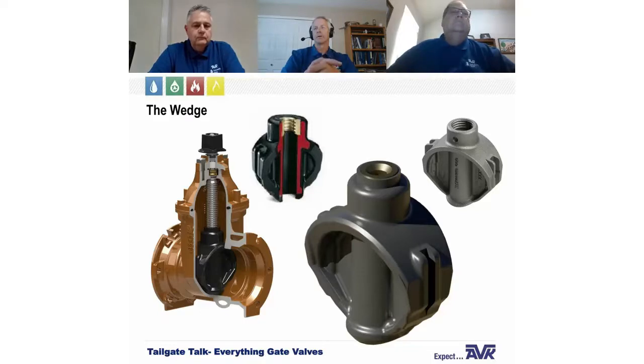Well, the primary thing about the AVK wedge design, as you can see in the center top up there, is that the wedge nut isn't loose. It is pressed into the ductile iron of the gate valve wedge. And we do that for two reasons. Number one, a loose wedge nut will sometimes wear through the rubber if it's opened and closed quite a few times because it'll shift back and forth as the valve is opened and closed. And the other reason is that there is no exposed ductile iron to the waterway. The rubber is vulcanized right up to the wedge nut.